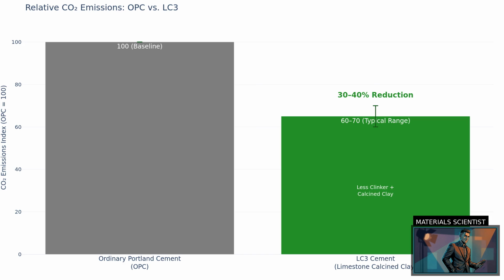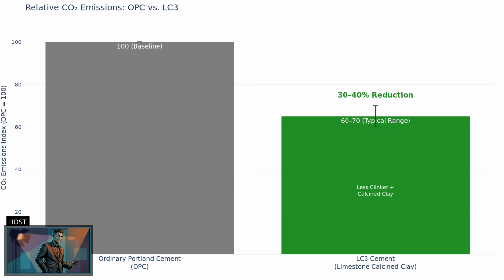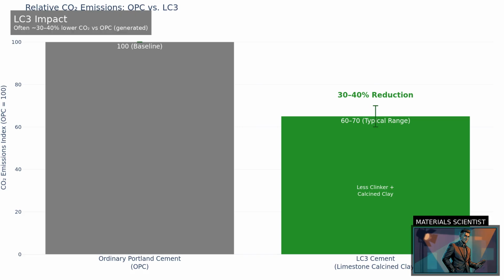A leading option is LC3, limestone calcined clay cement. In a typical LC3 blend, you replace roughly half the clinker with calcined clay and ground limestone. So you're diluting the carbon-intensive part with clay. Does that actually make a dent in the CO2 numbers? It can. Across many life cycle estimates, LC3 often comes in around 30 to 40% lower CO2 than ordinary Portland cement, mostly because you make less clinker, and the clay is calcined at much lower temperatures than clinker.